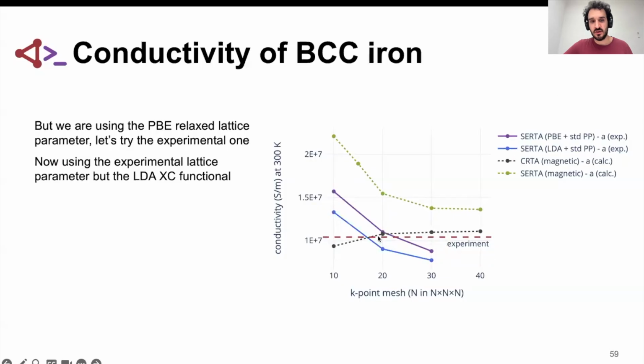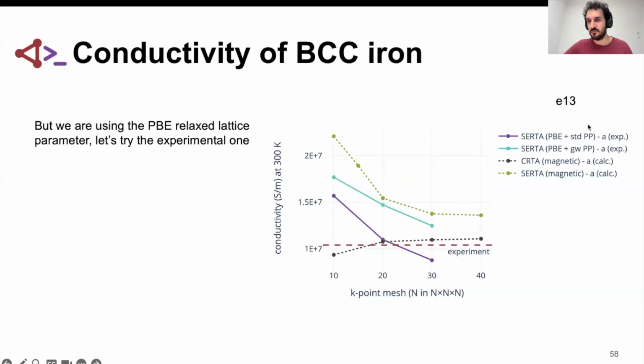So these are using different pseudo-potentials as well. The purple is using the standard pseudo-potential and the teal is using the GW pseudo-potential. So that is another important aspect to consider, which pseudo-potential we use. The GW ones are more accurate, so I believe that the result is going to be closer to the experiment. So it's more reliable, at least, even if it's not closer to experiment.